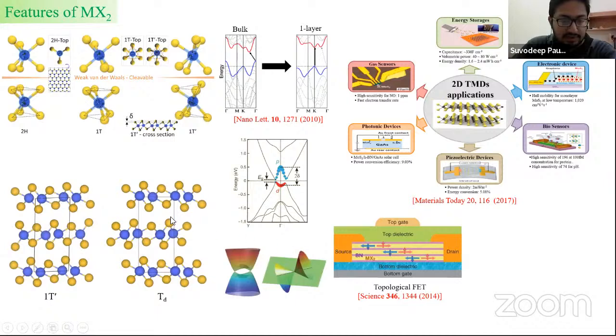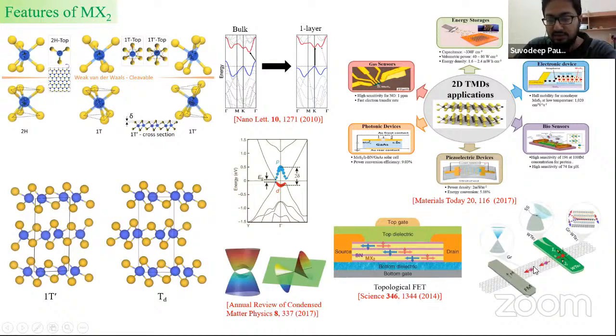And this is essentially a quantum spin Hall insulator, and such materials have been proposed to be used in topological FETs. The third phase we will be talking about is the Td phase, which has linear dispersion around the band touching points called Weyl points. And this is essentially a type 2 Weyl semimetal. And we know that type 2 Weyl semimetals, for example, Td-WTe2, has recently been demonstrated to show charge to spin conversion, which is why it has very good applications in spintronics. So keeping in mind some of these applications, we've done some phononic studies of different phases that I'll be elaborating in the next slides.